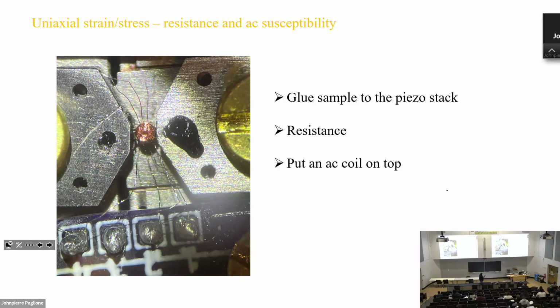So basically, you have a sample here. It's hard to see. You glue it to two sides of this, and on one side we put four wires for resistance measurement. On top of this, the company sells us this AC coil. One coil is $100, but I think it's worth doing this. You put this coil, and if it's a superconductor, you can see zero resistance and the Meissner effect at the same time. It's very nice.